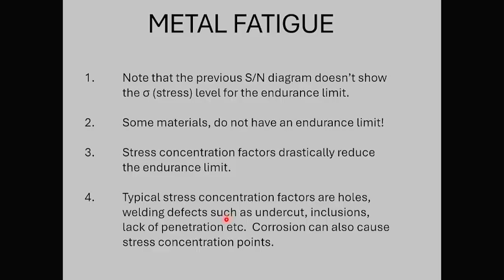For instance, what I've seen in industry: certain metals are not weldable. EN8 is not a weldable steel, and it's a common axle steel. People use it for everything, and then they wonder why their shafts fail. It's because the carbon content is too high, and they weld on it, and that weld has a minute crack. That's where the fatigue failure starts, and within 6 months, the shaft fails. So be careful on your material selection and where you weld and how you do it.